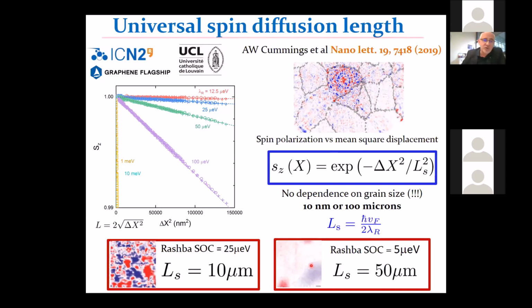And as a result, we could determine an upper limit for polycrystalline graphene deposited on silicon oxide, which is 10 micron, and for polycrystalline graphene deposited on boron nitride, we can go to 50 micron, just because the spin orbit coupling is decreased thanks to the flatness of boron nitride.